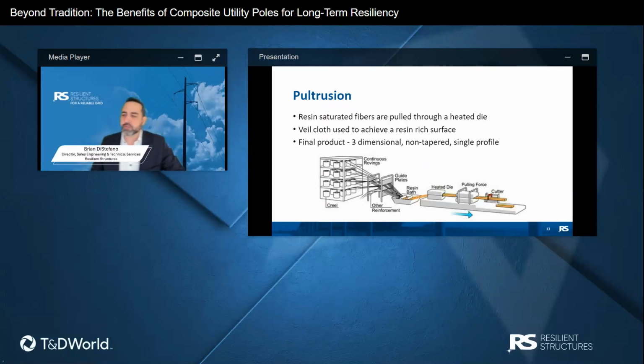So I mentioned pultrusion a few times. Just to go into the process a little bit more, pultrusion is a manufacturing process in which the resin-saturated fibers are pulled through a heated die. Very different than filament wound products. To form a resin-rich surface in pultruded poles, a veil cloth is typically required, which is what I mentioned in the last slide.